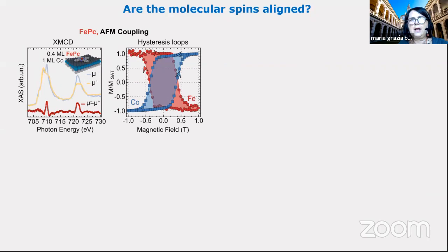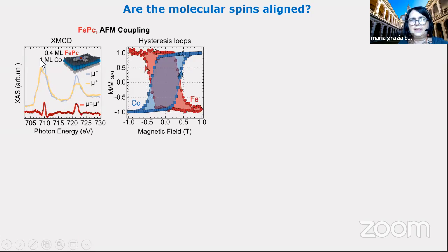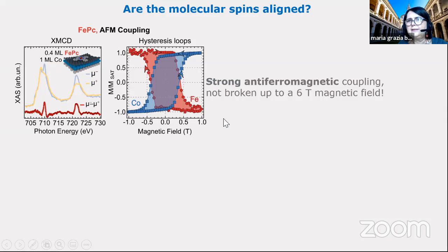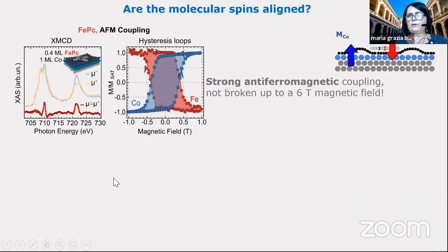So we made the same experiment, an XMCD experiment, now looking at the absorption at the iron sites. So for iron phthalocyanine, this is the absorption of iron, and this is the dichroic signal. The dichroic signal is different with respect to the cobalt one. The cobalt one has a positive and a negative part. These are both positive. If we calculate the magnetization, we will see the hysteresis loop, and this hysteresis loop shows a strong antiferromagnetic coupling that is very stable and not broken up to 6 Tesla of magnetic field. So this is the configuration.